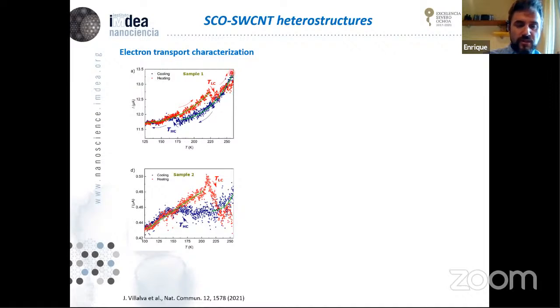So we start at room temperature, we cool down our sample, and then we see that when we reach the spin crossover transition temperature, there is a jump to a higher current state, and then it continues decreasing. So it looks like the current is detecting this spin crossover switch in the molecule. So the current on the nanotube is detecting the spin crossover switch.